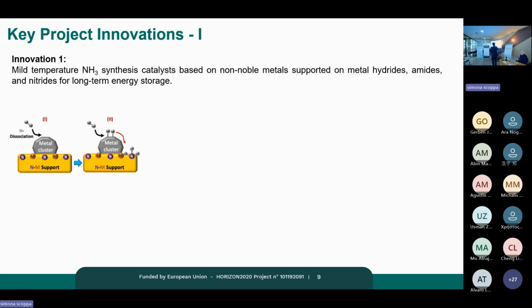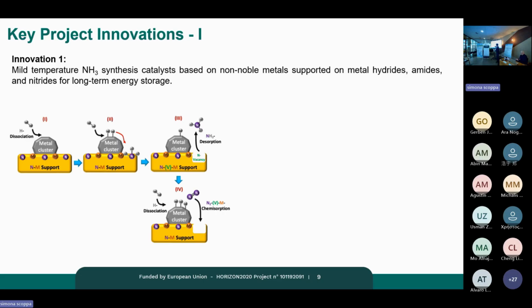All right, so I'm going to briefly talk about these few key innovations. The first one starts with the making of the catalyst. This cartoon illustrates what is called, in this case, a metal nitride containing a metal cluster. And the idea is that you try to leverage what's called a Mars-van Krevelen process, where your hydrogen starts to dissociate on the metal side. It reacts with nitrogen that is on the metal nitride at the interface, generates a vacancy by evolving ammonia. Once you have that vacancy, it is a strongly nucleophilic species, so it can actually attack